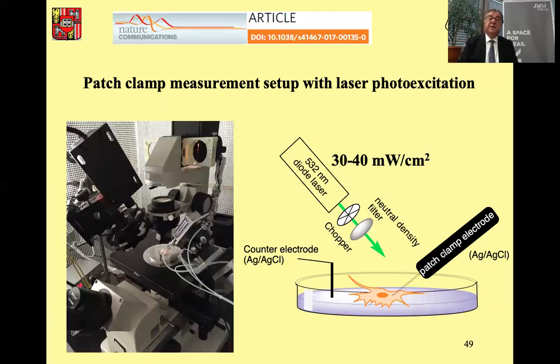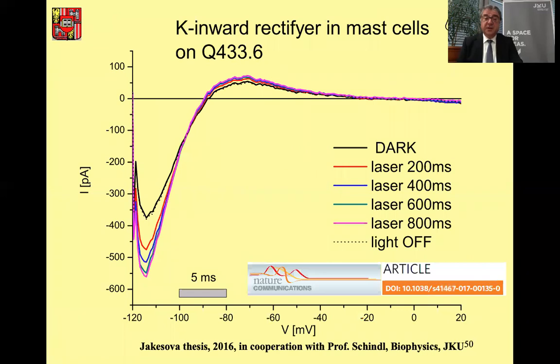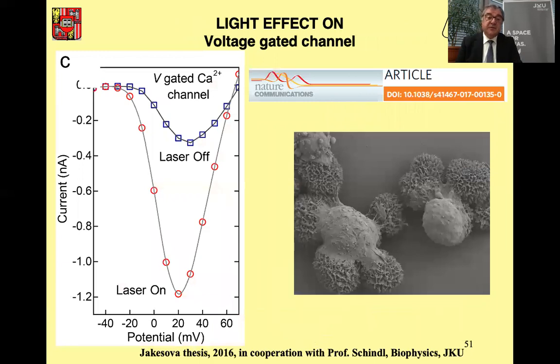And if you go and make patch clamp measurements and look at the cell response upon photoexciting the organic semiconductor underneath, it is very nice that you can observe that you can open the ion channels by using lasers exciting the semiconductor underneath. So this is a semiconductor layer. You put basically these cells on top of it. The cells don't absorb these lasers, but the bioorganic semiconductor absorbs it. And if you excite it, the living cell opens its channels. This is a work in collaboration with Professor Schindl. He moved also now to Medical University Graz. And then calcium channels you can open and close with light. So this is something quite interesting.